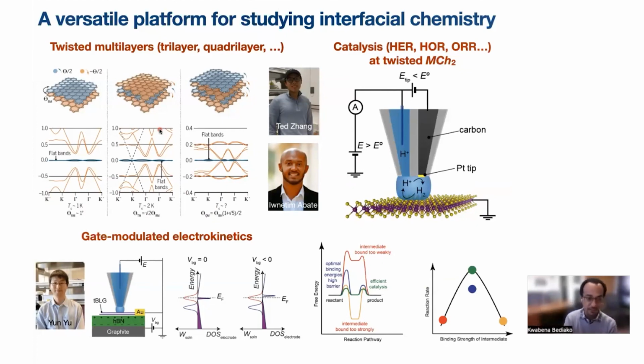We're extending it to multi-layers now, which gives us more possibilities for modulating the electrochemical behavior, many orders of magnitude more than what we've seen in twisted bilayer graphene. We think that there are significant implications then for catalysis, where the binding strength of the intermediate can be tuned by the angle, and then even using electrostatic gates, for example, to tailor this further.